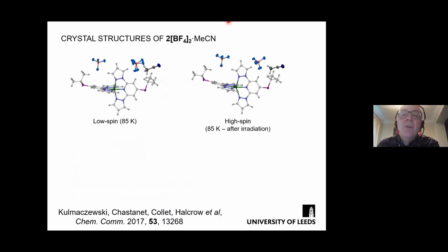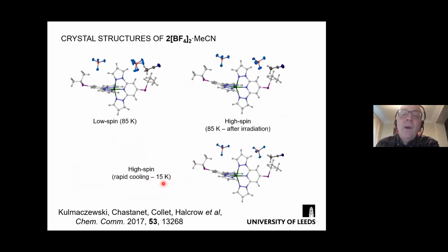Next, he measured this one, which is the acetonitrile solvate. For technical reasons, they had to measure at higher temperatures, but the same principle. There is nothing really unusual about these structures, and we got a very low temperature structure of the high spin form, and again, there's no difference.